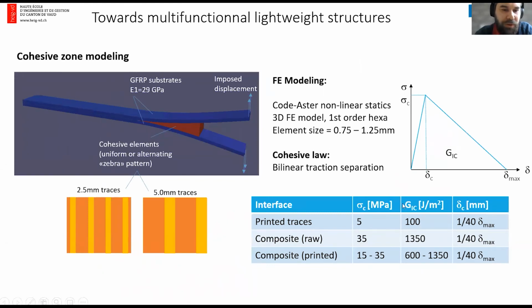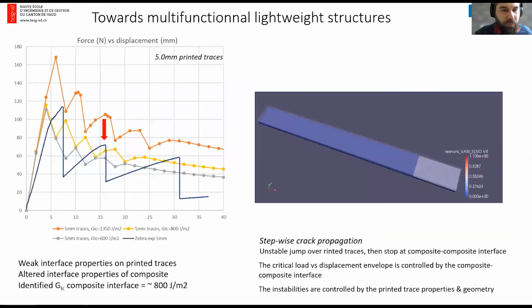To evaluate this, we did some cohesive modeling, modeling each region differently. So we have cohesive interfaces for the non-printed part and cohesive interfaces for the printed part. We played with the different parameters to identify the properties, and we could match the experiment. What is interesting is that in the experiment we have a load jump every time we reach a printed trace, and in the FE simulation we can see the same behavior. So we have unstable crack growth when we reach a printed trace and stable crack growth in between. This is just to show what we can do.